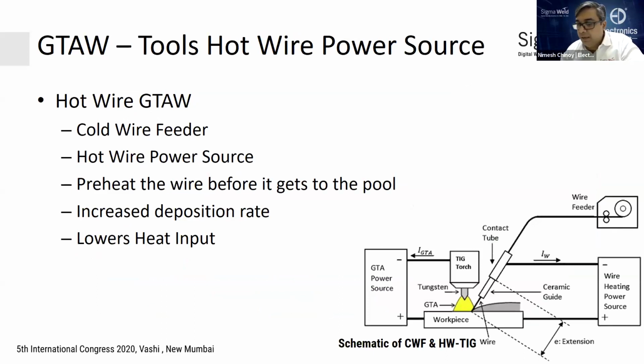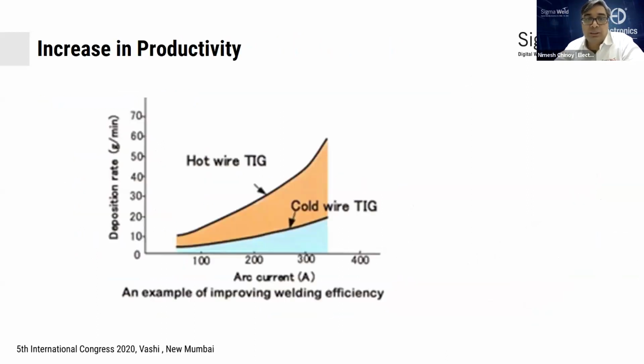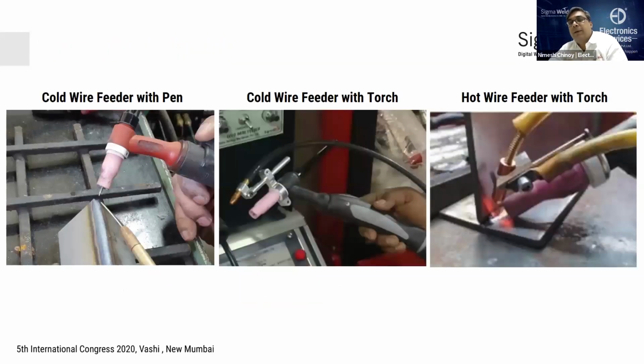You can even preheat the wire before welding. That's called a hot wire TIG. And that can even help you with a lot of speed increase in semi-automatic as well as fully automatic solutions. Comparatively, the productivity that you can get with cold wire or hot wire, typically if you take a 200 ampere range, you're doing about 10 grams per minute, or you can take it as 600 grams per hour. In cold wire, the same hot wire can give you close to about 1.8 kgs at the same current levels. So increase in productivity while keeping the currents low.